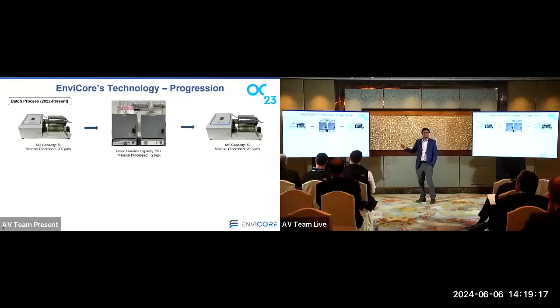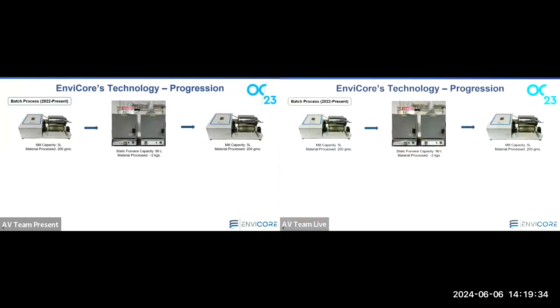Now, we developed this technology in early 2022, where we were just processing small batches of sample in batch mode, like just 200 grams in a roller jar mill of 5-liter capacity. We have static furnaces that can go up to 2 kilograms, but again, in a batch process. And finally, for the finish mill, we were doing pretty much the same capacity.